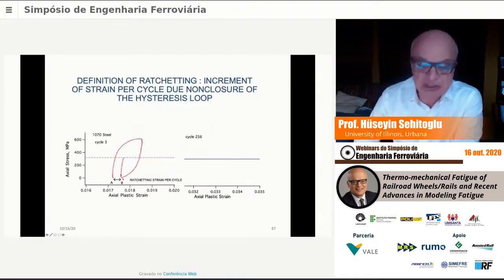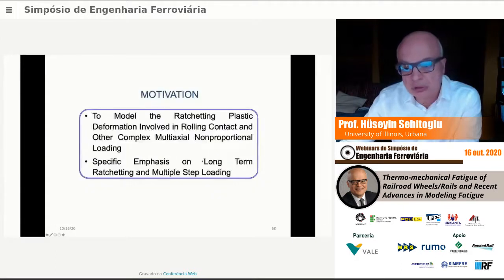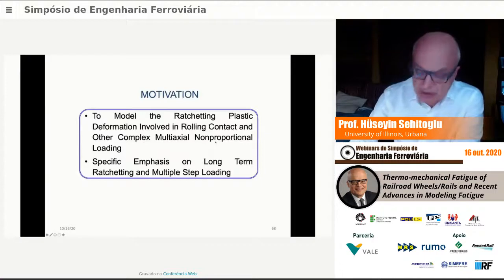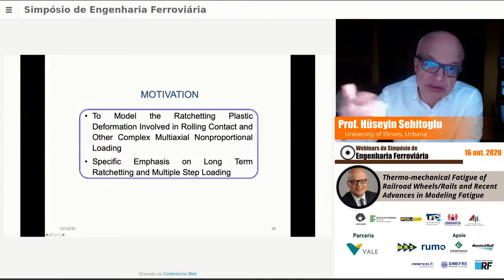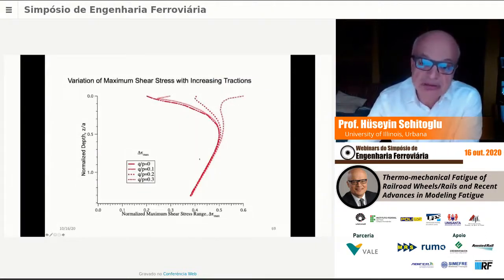Let's look at some fundamentals of ratcheting. So ratcheting means the net irreversible displacement or irreversible strain per cycle. That's the hysteresis loop. And if we see the cycle 3 here, this is cycle 256. So it does decrease with cycles in 1070 steel, not necessarily every material, but they're still ratcheting here, right? But the situation we have is very complex. It's multi-axial and also non-proportional. Non-proportional means the plane of maximum shear is rotating. It's not constant. So we are also interested in long-term ratcheting and also multiple step loading.